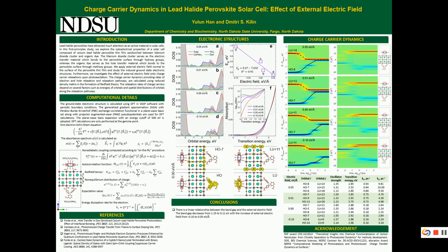For semiconductors, we shine light, so there will be hot electrons and hot holes. These hot electrons and hot holes will relax to the band edge through lattice vibrations. So we just characterize these processes. This is a DFT study for the band structures. We do our calculations in VASP with a PBE functional. This is spin-restricted DFT. And then for the charge carrier dynamics, we have home-made scripts, so there are equations.